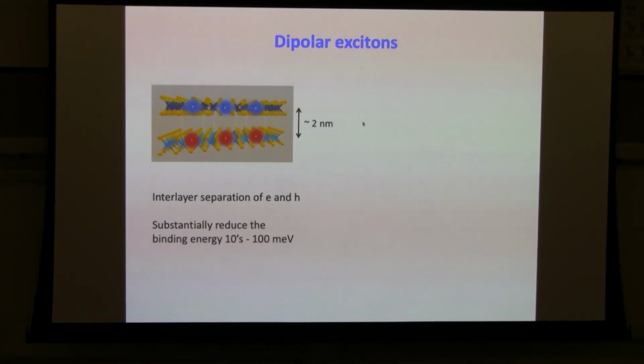So that's why we really need to put them into two different layers to insert an insulating barrier to separate the electron and the holes to reduce their wave function overlap, so that we can really lengthen their lifetime and still maintain the strong binding energy. Because of this spatial separation of the electron and holes, the exciton binding energy is quite a bit reduced to about tens of milli-electron volt to about 100 milli-electron volt.